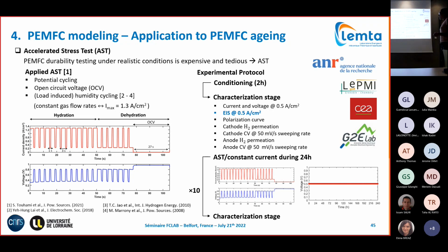Therefore, we developed for our research an accelerated stress test that concerns electrode aging and membrane aging. It consists of potential cycling, which would primarily create electrode aging, primarily of the cathodes. Open circuit voltage operation would primarily induce chemical aging of the membrane, and then humidity cycling. In our case, humidity cycling was load induced, meaning by playing with the